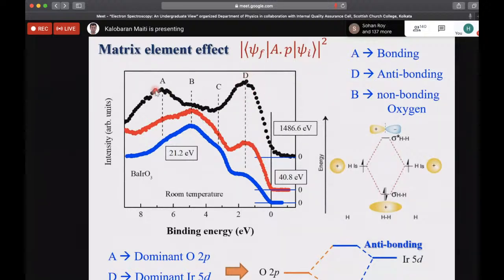In this one, you can see that oxygen 2p is there as well as iridium 5d. Here also you have oxygen 2p and iridium 5d. But you can see that the change of this intensity is much stronger here compared to the change of this intensity that you have here. Now, since both this peak and this peak have strong iridium 5d states and oxygen 2p states, you can easily say that both of them are contributing to these two peaks. Means that they must be the hybridized states of iridium 5d and oxygen 2p. So from that experiment, you can say that this is basically the bonding states.